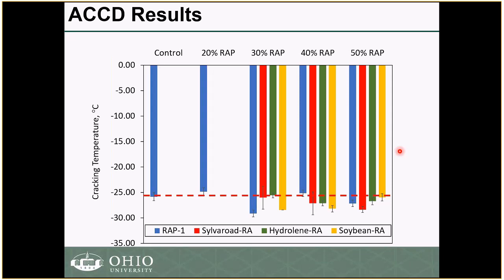For the cracking temperature, this is based on the ACCD. This is the low temperature cracking. Again, what we have noticed is that the virgin asphalt binder, to a certain degree, controls the cracking temperature of the mixture. So what I'm saying here is that using a softer binder, a 64-28, in general, with such a binder, we are able to go up to 50% RAP without really affecting the low temperature cracking resistance of the mixture. So using, again, the right virgin asphalt binder will result in a low temperature cracking resistance that would be equivalent to the control.